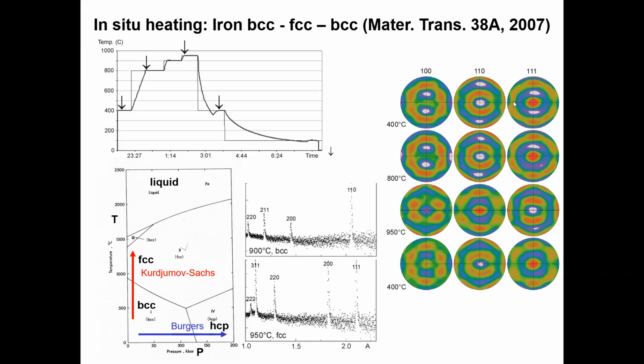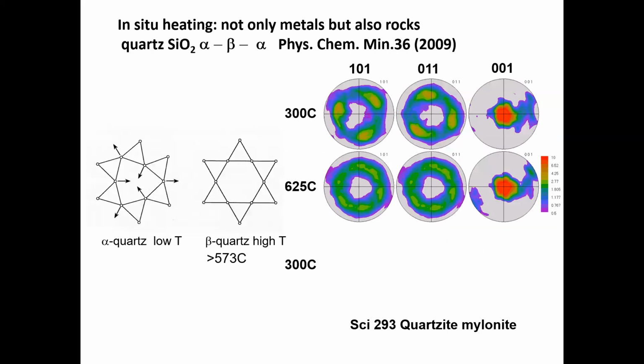So first at low temperature in BCC, we have a maximum at 111. And then it switches at 950 degrees in FCC to a maximum at 110. And remarkably, as you cool it again, it goes back more or less to the same texture as it was before. So there is a memory effect. And on this slide, I show you this.